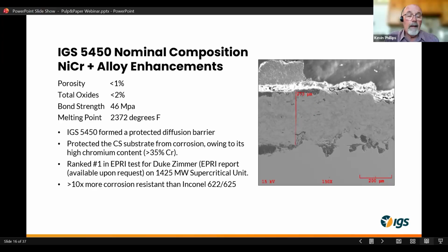There was an EPRI study done a number of years ago on this particular alloy composition that we've developed. It was done in a supercritical PC fired coal burner, which is also very subjected to high corrosion rates. And it was found that our 5450 composition was actually 10 times more corrosion resistant than Inconel 625, 622. So it's an excellent alloy to be considered for areas within the recovery boiler that would need assistance in protection against sulfidation corrosion.